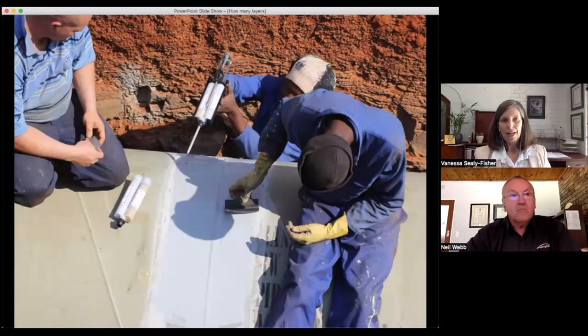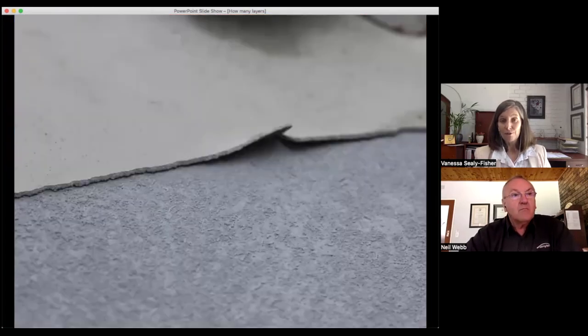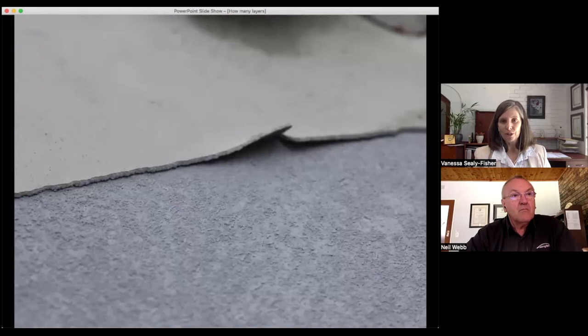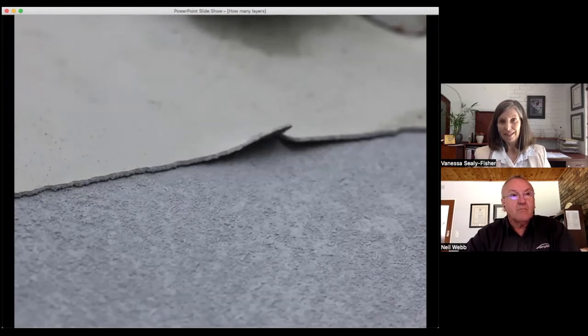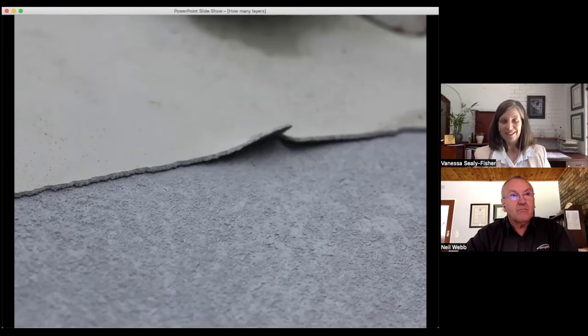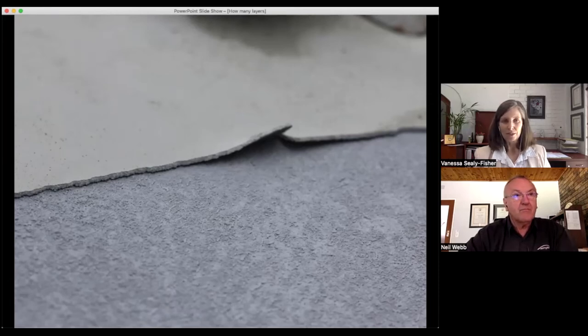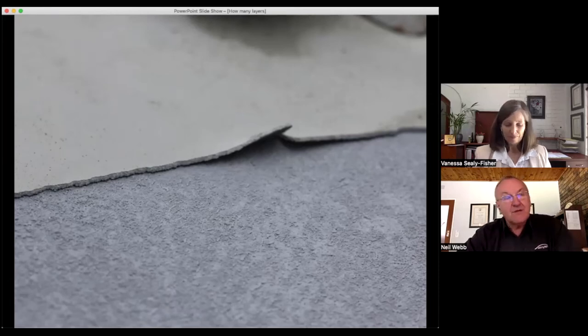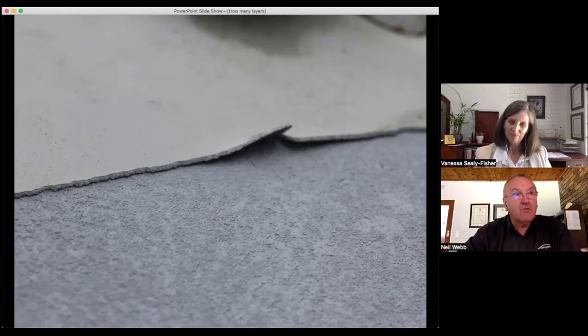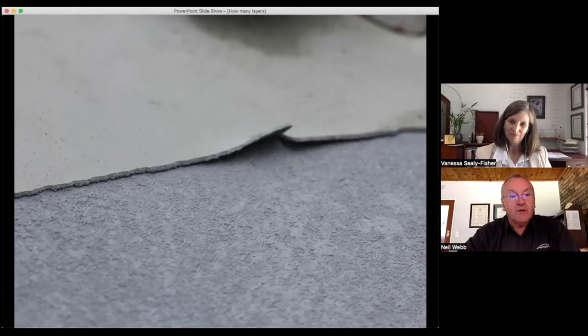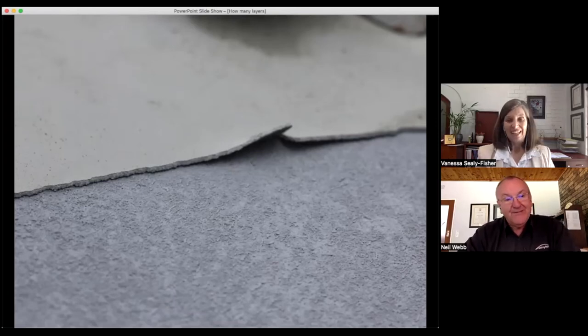What happens if the ratio is off? The top might be fine, but underneath, instead of being rigid polyurethane, it's actually flexible polyurethane unintentionally and not adhering as it should. In a particular example, the ratio was so far off I don't know you could call it polyurethane—it was chewing gum.